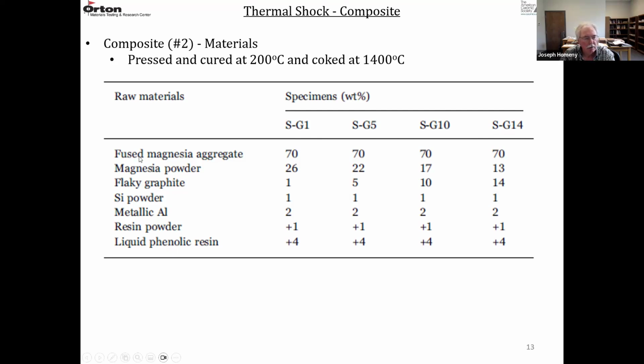This is the formula. They have fused magnesia. Of course, they're aggregates, then a finer magnesia powder. So the aggregates were kept constant at 70%. The magnesia powder decreased from left to right, and then the flake graphite content replaced the magnesia powder. So we're always looking at 27 weight percent combination of magnesia powder and graphite. So SG1 has 1% graphite and 26% magnesia powder. And then we'll get up to SG14, that's 14% graphite. And then the magnesia powder is reduced to 13%. So 1, 5, 10, and 14% were the flake graphite contents.